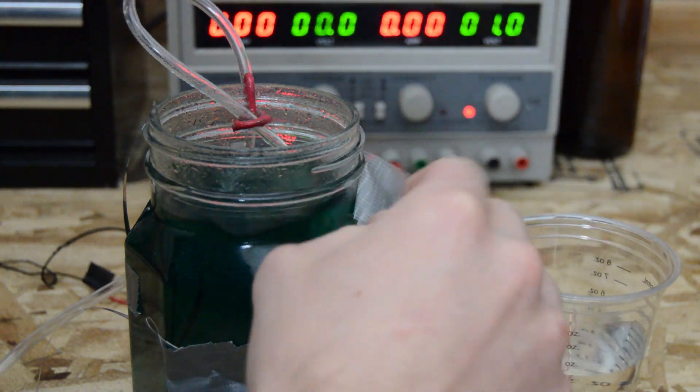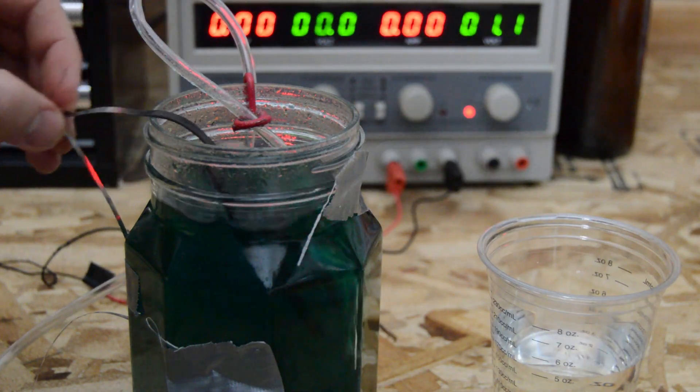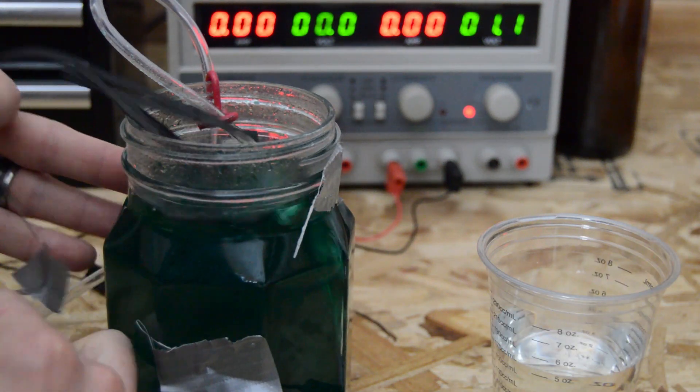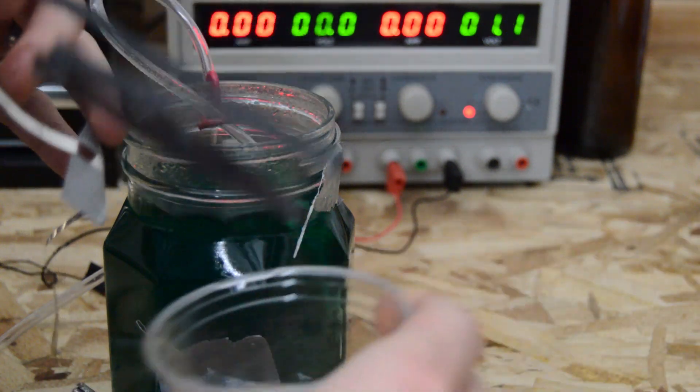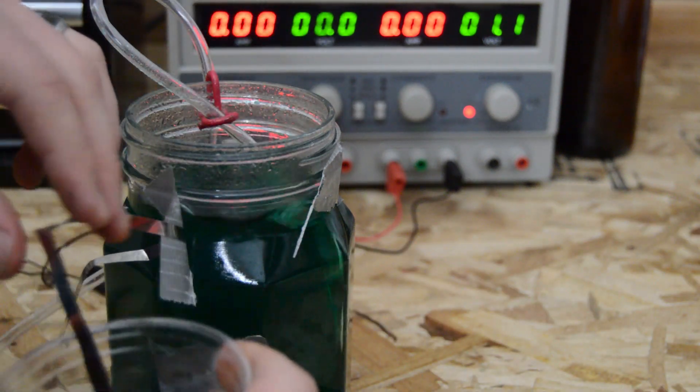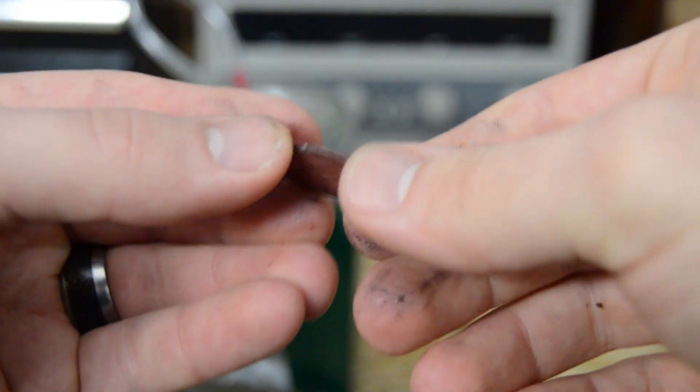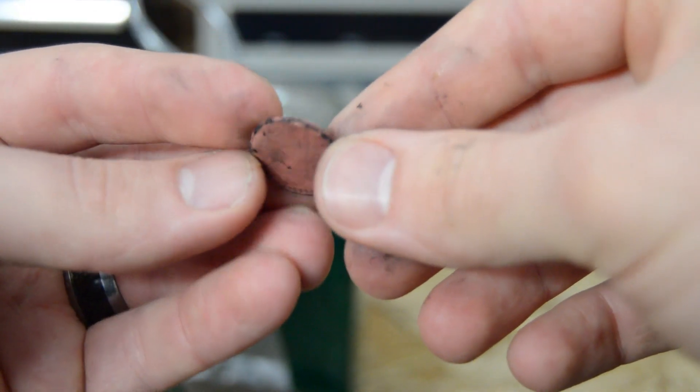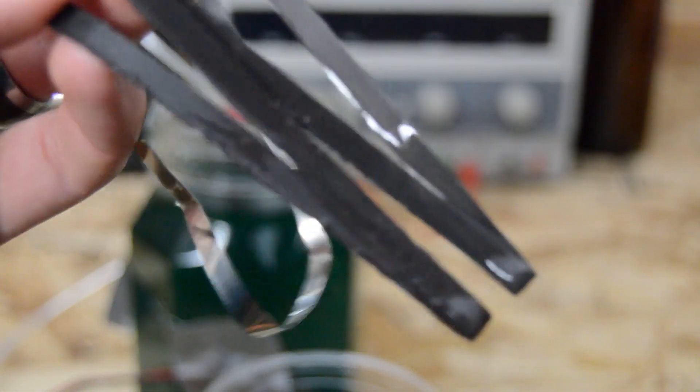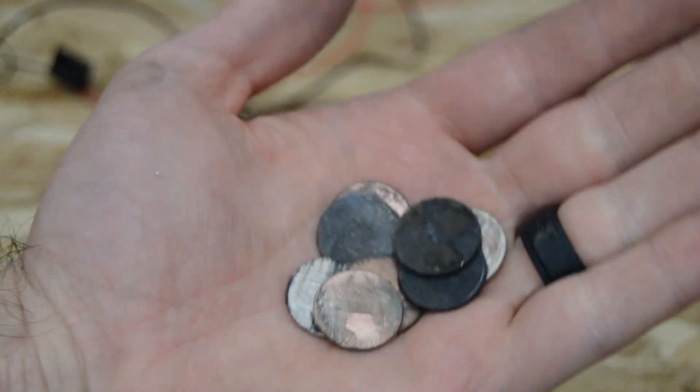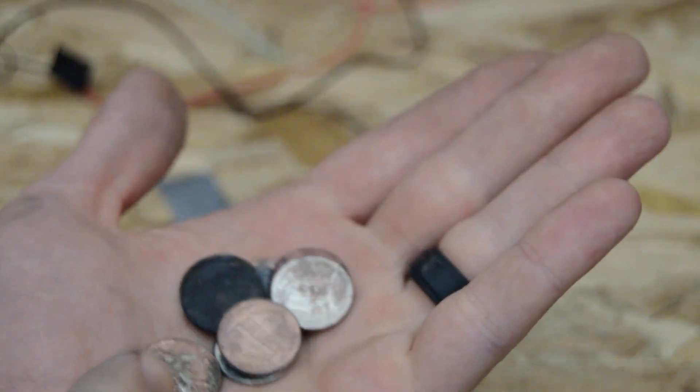Now, I was a little stupid when I started plating because I was careless and didn't pay attention to how I plugged my leads into the power supply. This resulted in attempting to plate nickel strip with copper from the penny. Besides not being the plating result I wanted, I also dissolved a bunch of metallic contaminants into my plating bath. So don't be like me and pay attention to what you're doing. Positive goes with your nickel electrode, which is your anode, and negative goes with your part, which is the cathode. The nickel strip was basically unusable at this point because it was covered in plated copper and a thick black sludge. I didn't want to risk further contaminating my bath so I just made another nickel electrode.